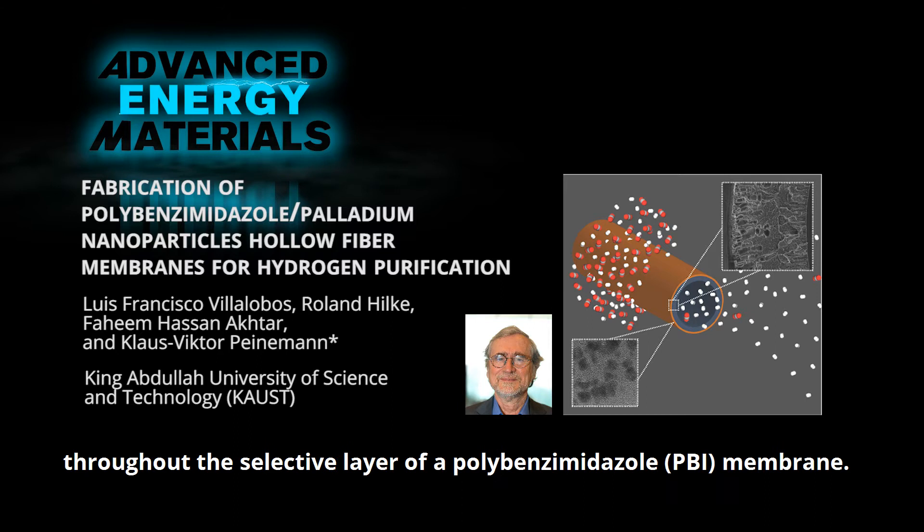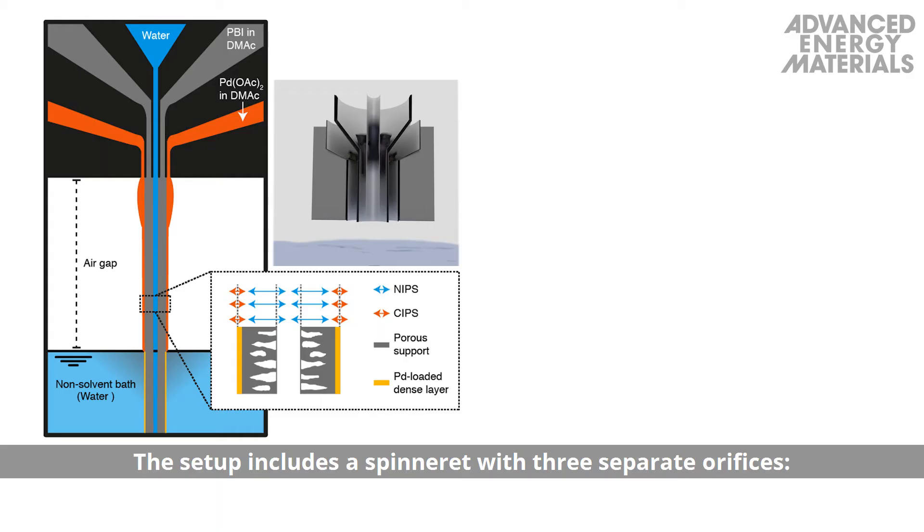The setup includes a spinneret with three separate orifices, one each for solutions of PBI and palladium-2-acetate in dimethylacetamide, and the other for water, the non-solvent.